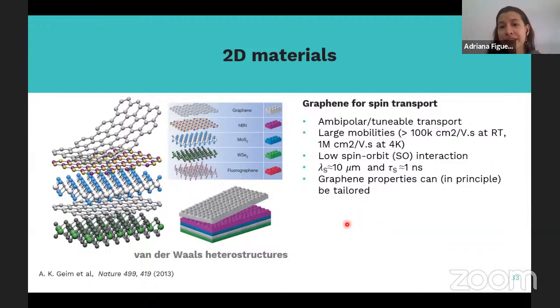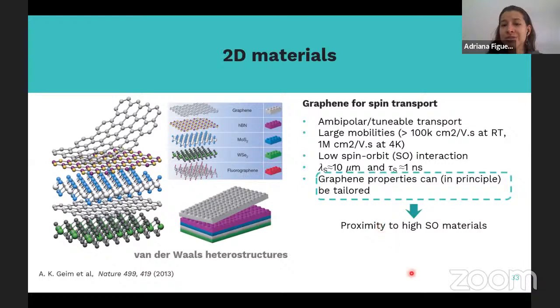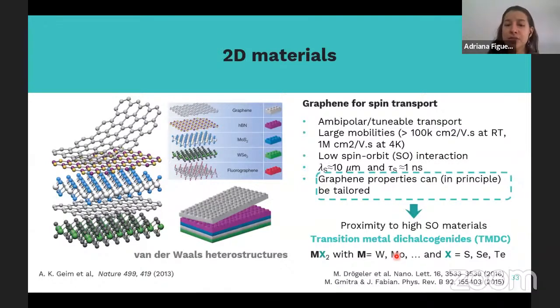But you cannot really control that spin transport in graphene because of that low spin-orbit interaction. So you want to introduce some sort of spin-orbit coupling in the material by proximity to materials that have a high spin-orbit coupling, such as transition metal dichalcogenides, which are also 2D materials. And then you can create these van der Waals heterostructures to take advantage of both the electronic properties of the graphene and the spin-orbit coupling properties of the TMDC.